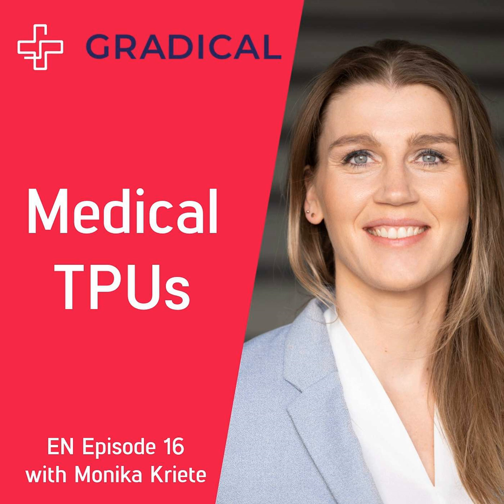Yeah, so TPU is very well known for having a very high strength, especially with thin walls. This is one of the main reasons why TPU is used in a lot of catheter applications, for example. It is very durable, with great abrasion resistance. And one unique property of TPUs is the in-body softening, which means if you heat the TPU up to, let's say, body temperature, the flexural modulus will drop, so it becomes more flexible while still keeping the tensile properties pretty much the same. This can be very beneficial for medical devices where you want to minimize the discomfort for the patient if you introduce a catheter into the body, and also minimize the risk of any rupture inside the vessels.